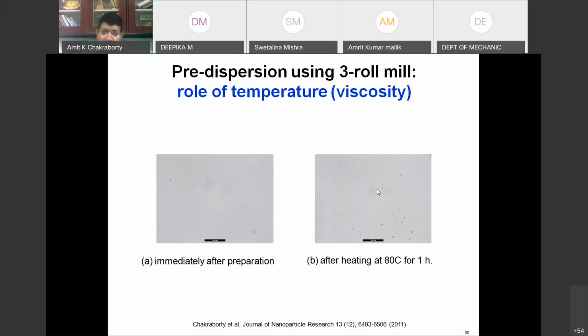Similarly, we have also studied the role of temperature. If you do it at room temperature immediately after preparation, and if you heat it at 80 degrees Celsius, after 1 hour you see some particle formation. Why did we study the influence of temperature? Because these resins have to be cured with a hardener at a certain temperature. It can be 80 degrees, it can be 120 degrees for several hours.